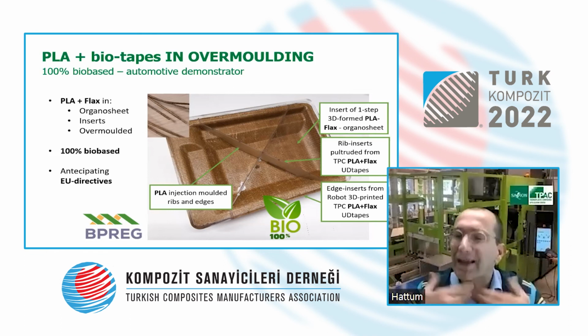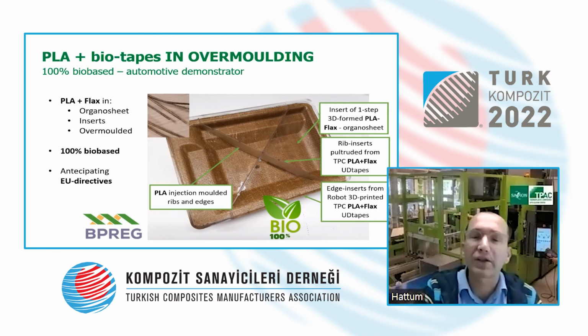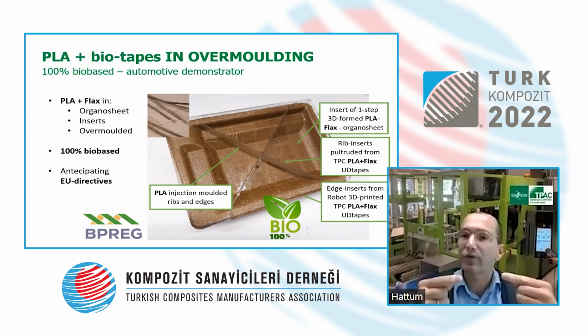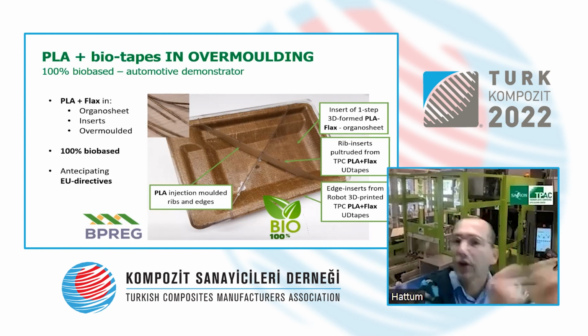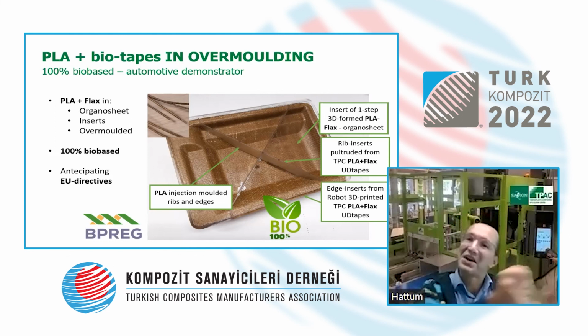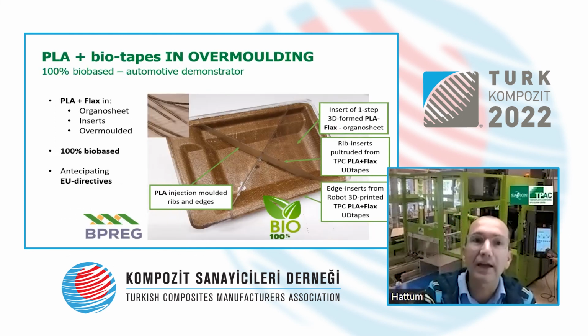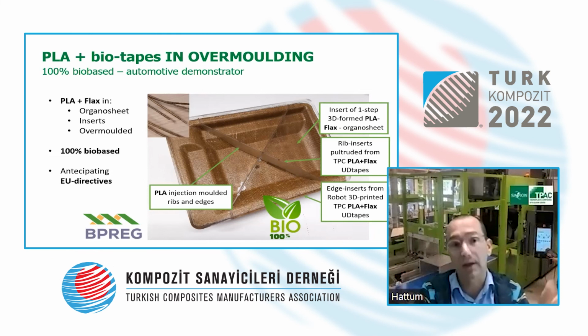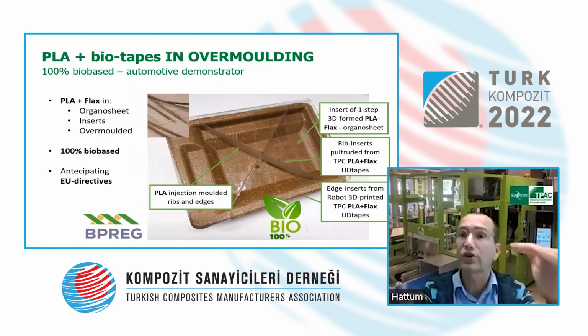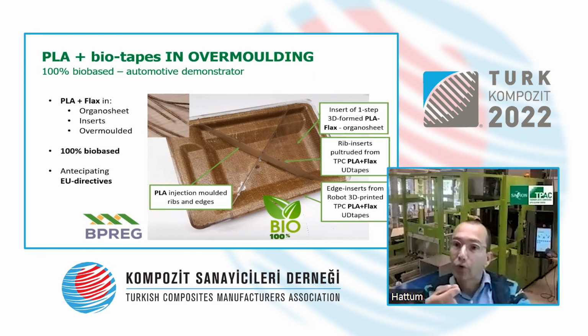In the picture, I must admit, I'm lying a bit because yesterday I was looking for the correct picture. I say it has local stiffeners. As you can see in the picture, this specific picture does not have, but I can guarantee you, if I would have found the other parts, we keep on losing them for some reason, it's here. We can do exactly the same as we've seen here, but now with PLA, a bio-based, biodegradable polymer, plus a flax fiber. In organo sheets, the inserts were made out of that material, and we overmolded it with the same material. Actually, you can see the little sticks on the top left-hand side. They are the pultruded sections that we then 3D printed to integrate in this part.